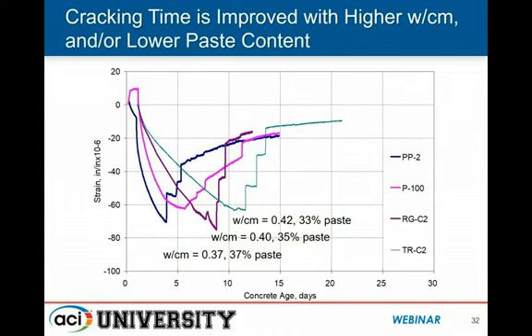This figure illustrates exactly what I'm getting at in terms of tweaking the concrete mixture, because we're trying to promote mixtures with cracking times that are longer. And as you can see, on the very left-hand side, the blue line is the lowest water cement ratio set of data that we have. It's also the highest paste content. As we move towards the right and go from the blue line to the pink line, we have a slight increase in the water cement ratio and a slight reduction in the paste content. And we continue to see that benefit as we move further and further. What this tells us is what we typically are doing in the industry to promote early strength and higher long-term strength is going in exactly the opposite direction that we want to go with respect to cracking.